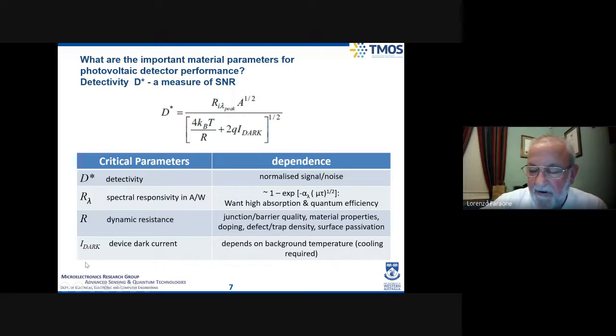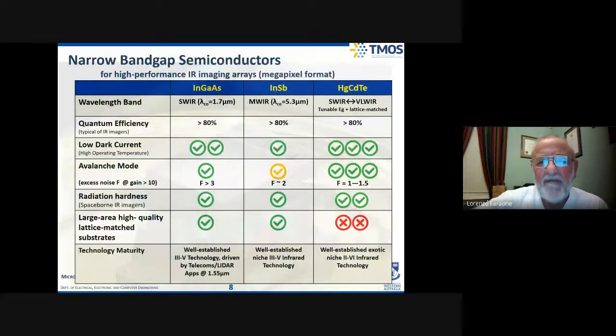So in a very simplistic point of view, if I look at different wavelength bands, this represents the shortwave infrared, the midwave infrared, and the long wave infrared, or pretty much all bands. The technology gets more difficult the longer the wavelength I'm trying to detect, because the energy band gap gets narrower and narrower as I go to longer wavelengths, and so the generation recombination rate increases, and the noise increases.